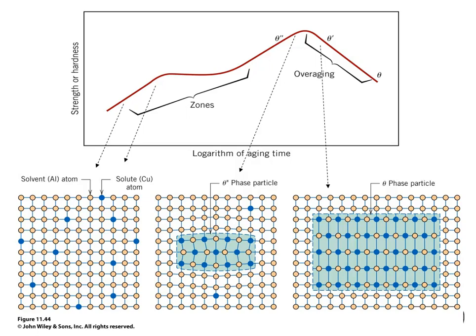But look at how there's no real grain boundary. We've still got a correspondence of each one of those atoms back to the parent lattice. They're lined up exactly where they would be if they were still in the parent aluminum lattice. As such, notice how everything is bending in. You've got a lot of atoms with diagonal lines connecting them, and that's representing those atoms not being in their equilibrium positions and being strained. Those strain fields extend all the way out into the parent aluminum lattice and can impede dislocation movement all the way through the lattice, and that's where you get your strength.